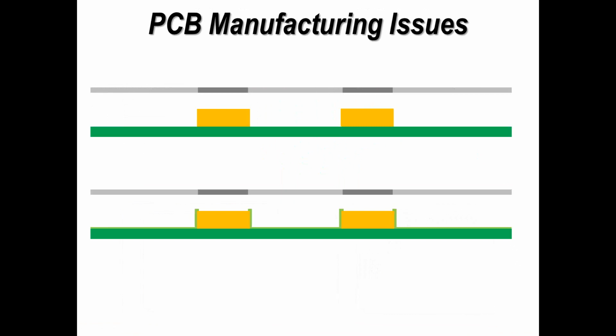Now, here we've got pads on the surface of the printed circuit board, and the pads are well defined. They've got straight copper walls after the fabrication process. But if, for whatever reason, the consistency of the board fabrication is not good enough, then we can actually get the copper at the top, on the top surface, to be a slightly different dimension than on the board surface.